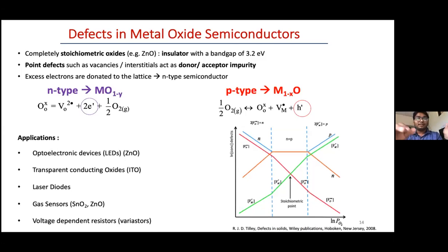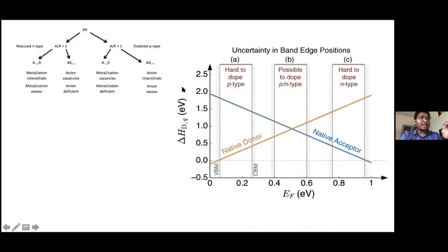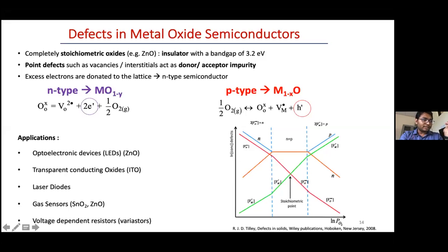You can see these things from the diagram here. So this shows the concentration of defects on the y-axis compared to the oxygen partial pressure of synthesis. At higher and higher oxygen partial pressure, you would expect that it is oxygen rich, and at lower oxygen partial pressure, it will be deficient in oxygen. So the oxygen vacancy concentration is much higher at low oxygen partial pressure. On the other hand, if it is in an oxygen-rich atmosphere, you will see that the metal vacancy concentration is much higher. And somewhere in between, it has a balance between the two. That is the stoichiometric case, which hardly happens in real crystals.